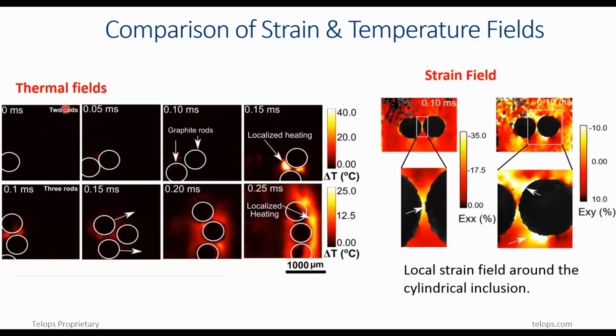And the digital image correlation showing strain fields and temperature field here, where the axial strain in the polymer region between the solid inclusions is very significant compared to the other locations, and the shear strain is high on locations where the temperature is high. This suggests that high shear deformation near those solid inclusions causes relatively high motion between the polymer and the solid inclusion, which causes the heat generation and the following temperature rise.